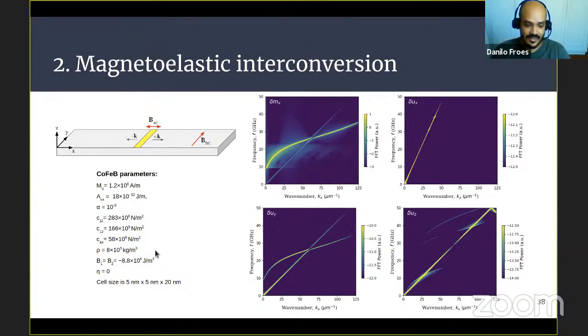But it does have a significant magnetostriction. It's a negative one, both B1 and B2. I believe the MuMax group chose this material because of this frequency region of the anti-crossing being in the 20 gigahertz range. And the difference, the delta frequency here, is half a gigahertz, so it's big, so it can be readily seen. We chose this material so we could compare our results with them, to make sure they were matching and going in the same direction.